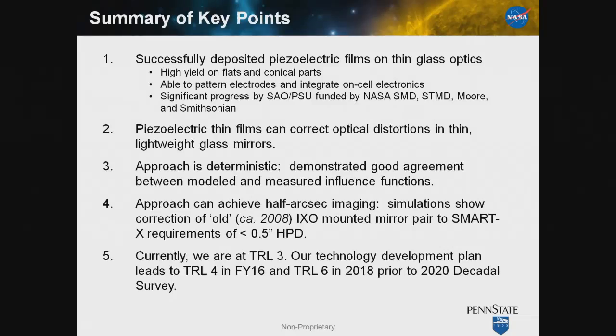So to summarize, we have successfully demonstrated that you can grow piezoelectric thin films with large piezoelectric responses on thin glass optics. We've demonstrated high yields on both flats and slumped optics. And we've demonstrated the ability to pattern those electrodes at the spatial scales that are required. And we're very thankful for the funding for this work that's come from NASA and the Moore Foundation, as well as Smithsonian Astrophysical Observatory. The piezoelectric thin films allow you to correct optical distortions in thin, lightweight glass mirrors. And we predict that we should be able to achieve about a half arc second resolution.